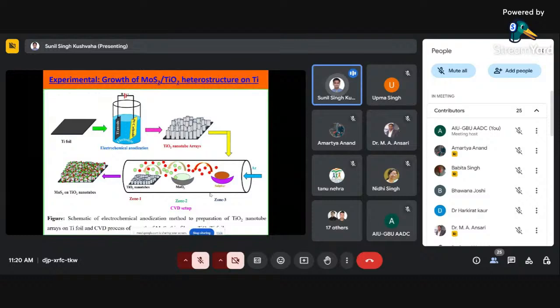So I will take some examples of what we also do in our lab to make these different materials. We started with, for example, TiO2, and we have grown this TiO2 on the titanium metal foil. That is again a flexible foil. Then we use a simple electrochemical anodization process, and after that we get these TiO2 nanotubes, and then we get some 2D materials. As I mentioned, it requires a 600 to 700 degrees Celsius process when we are growing some MoS2, and then we have coated this one. So of course, we can't use substrates which have very low temperature limits, like polymer and other things. So that's the reason we have selected these metal foils.